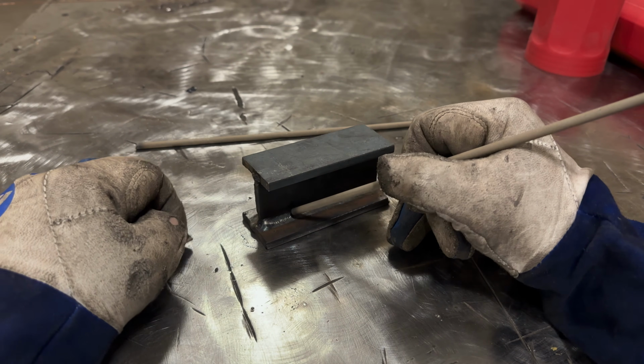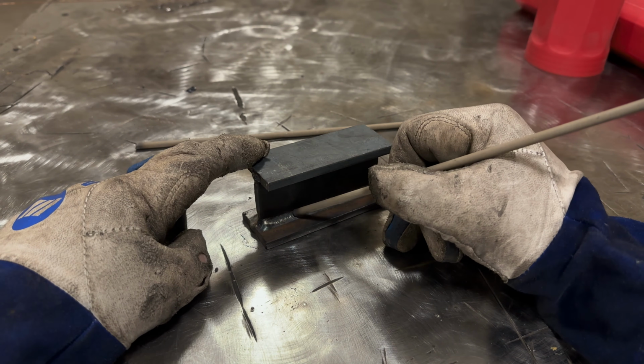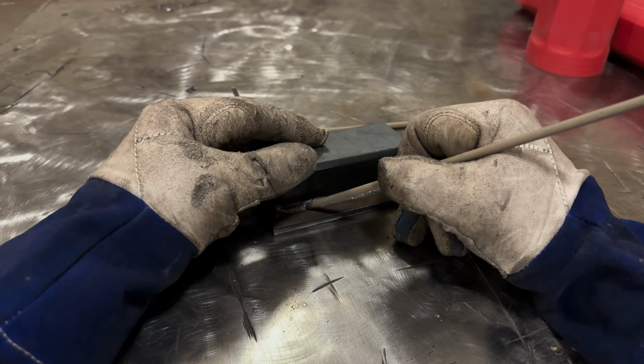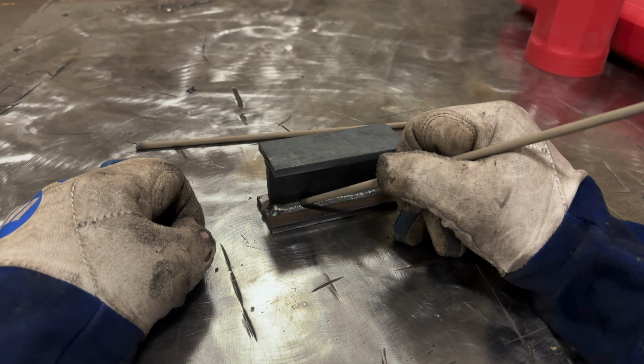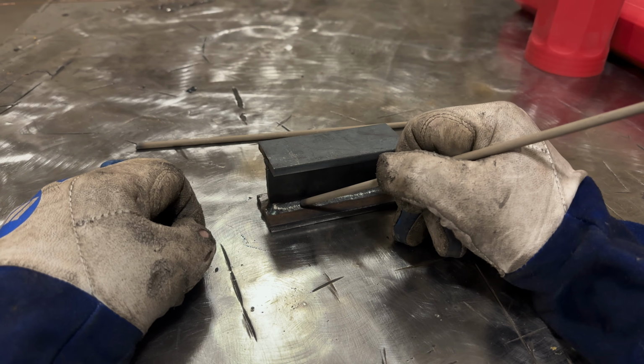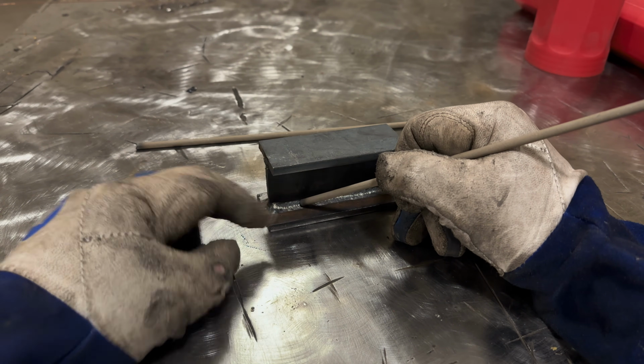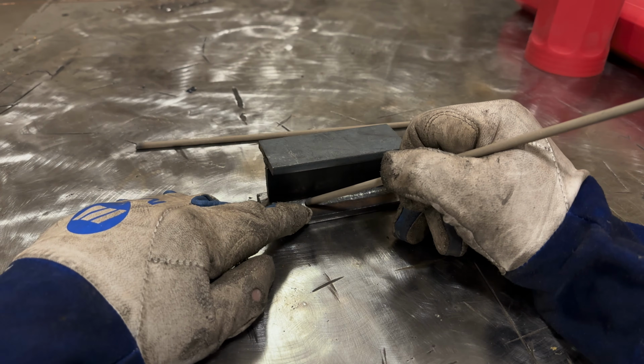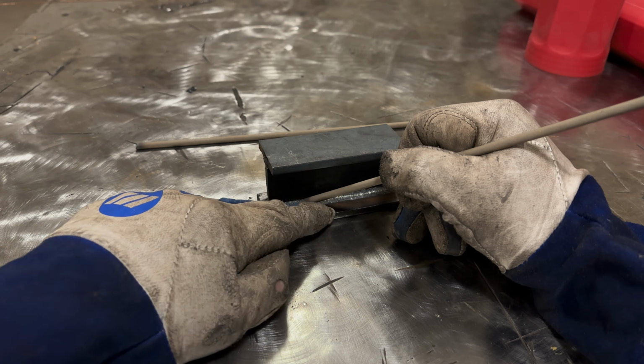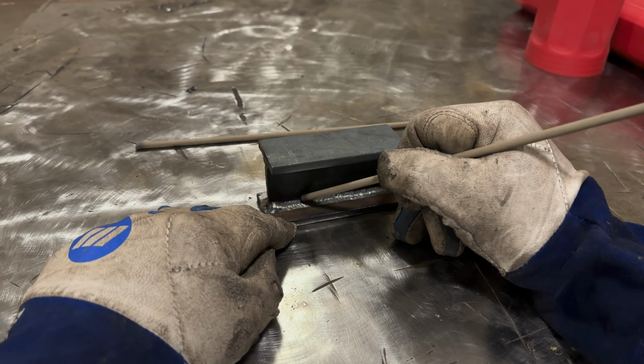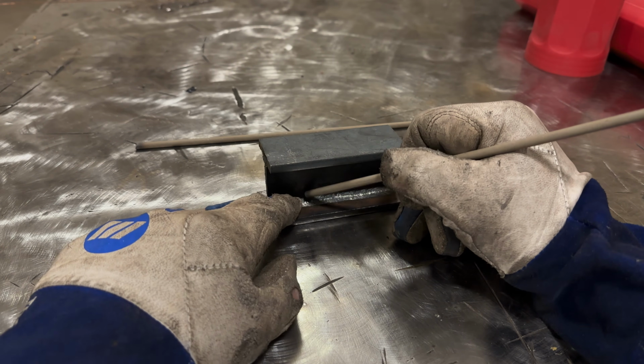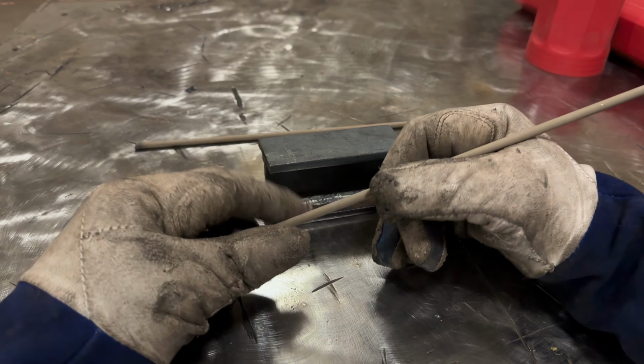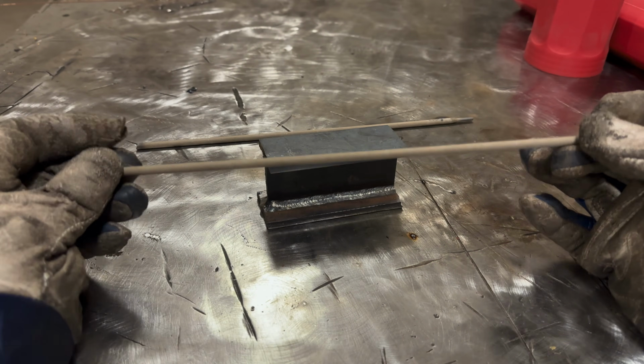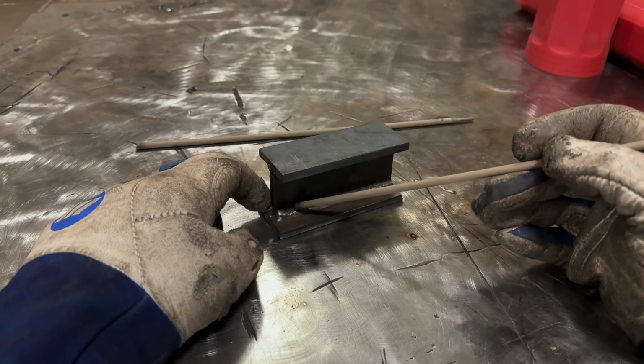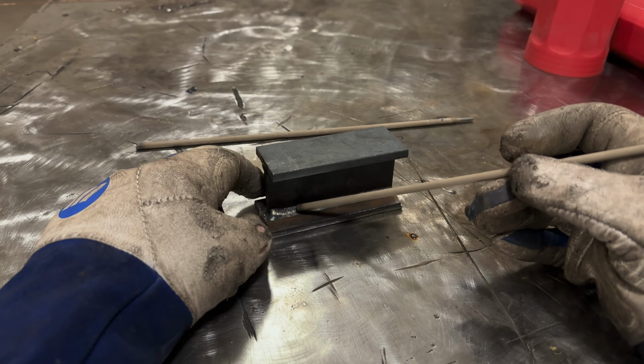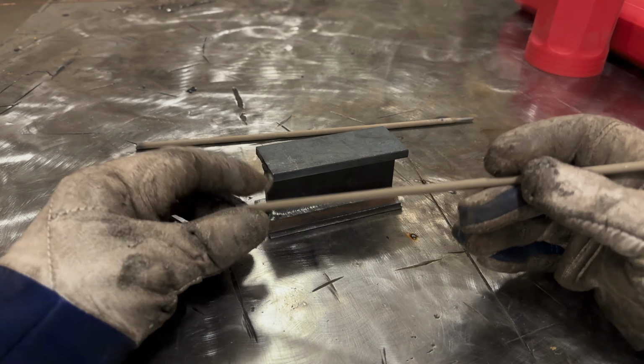And if you don't keep that nice pressure pushing that flux up into that molten puddle, it's kind of like melting a crayon off. If you're not putting that pressure on there, your arc gap will extend a little bit too long, and it doesn't take too much before it either blows out the side or ahead of your puddle, and then your flux just wanders and it just gets all over, and your arc is uncontrollable. Very easy with 6013. Some of the other rods like 6010 and 7018 I find less likely to arc blow.